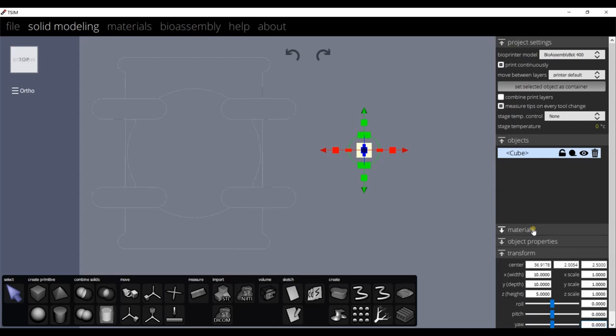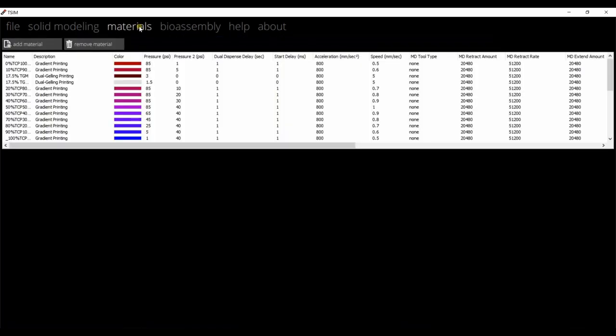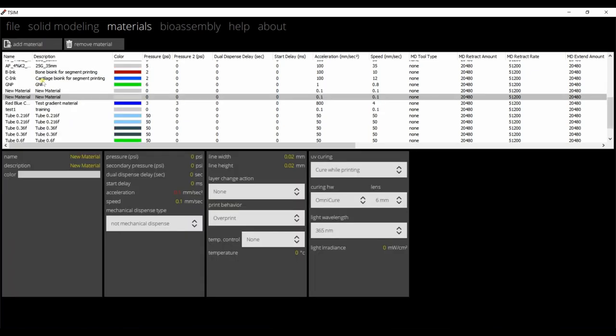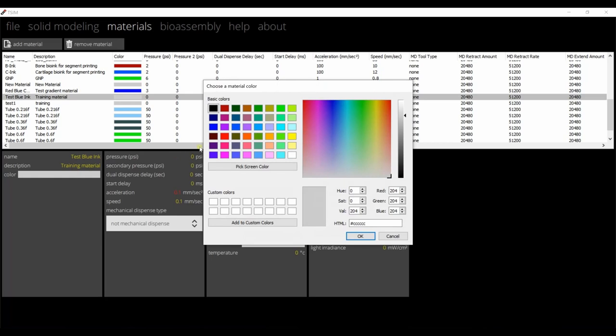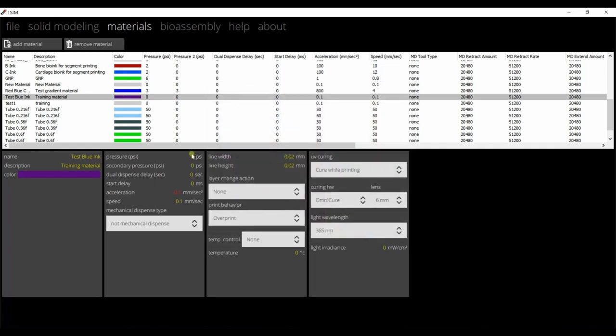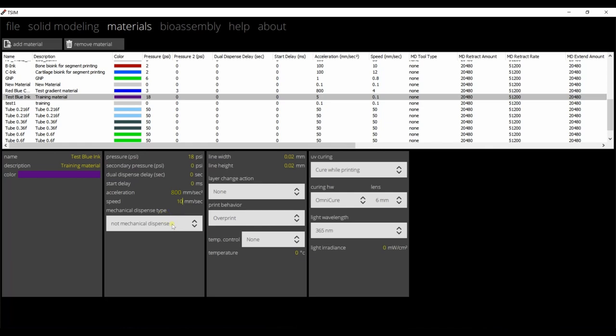Click on Materials menu on the top and click on New Material. On the bottom half of the page, we have various options for the new material. We give a name to the material and a short description. The color is for visual representation only in TSIM and HMI. This is useful to visualize different materials if you are working with dual or multi-material projects. Update the extrusion pressure for this material. In one of the previous steps, we have optimized extrusion pressure for this material, which was 18 psi. Secondary pressure is needed while working with dual extrusion printhead and this will be the extrusion pressure for the second material. Start delay options will be needed for materials that take a moment to begin extruding. Change the acceleration as needed, preferably higher acceleration of 800 mm per second squared. Change the speed as needed. Here we will be using 10 mm per second. Next is the mechanical dispenser type. We are not using any mechanical dispenser, so we will leave it as is.